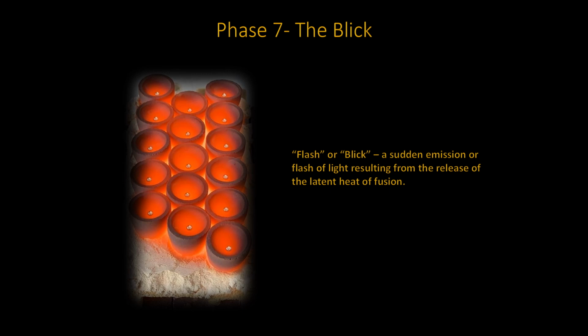As it solidifies, there will be some latent heat of fusion within the bead. This latent heat will cause a sudden emission or flash of light, which will also result in a considerable rise in temperature, which will last for a short period of time. This flash is the blick, and it signifies the end of the cupellation process.